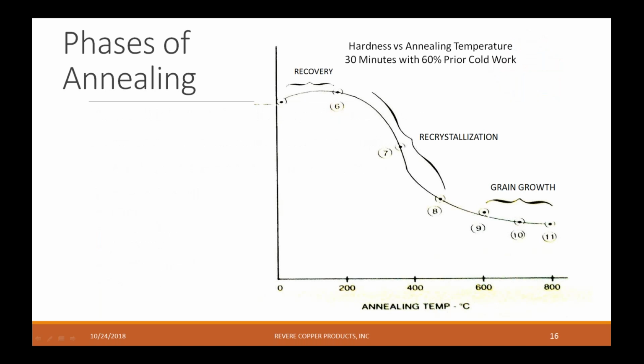This graph shows the hardness versus annealing temperature if it's annealed for 30 minutes with 60% prior cold work. So if you think back to that other chart I showed, 60% means it was spring hard, or H08, and then it was annealed for 30 minutes. And you can see that at 600 degrees, you start getting grain growth. At 400 degrees, you have recrystallization happening. So depending on how much grain growth a customer wanted, that would be determined by the temperature, and then also time.